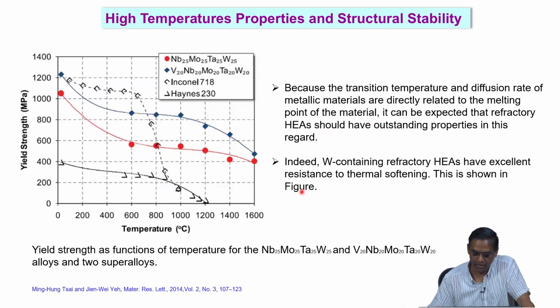For example, tungsten containing refractory alloys have an excellent resistance to thermal softening. This is shown in the figure. So, what you are seeing here is niobium, molybdenum, tantalum, tungsten, all in equal proportion, and then you have the vanadium, niobium, molybdenum, tantalum, tungsten alloy. You can see that the yield strength shows very small change with the increasing temperature. On the other hand, you see this Inconel has got a drastic transition beyond 600, and Haynes also softens much more rapidly as compared to these two high entropy alloys.